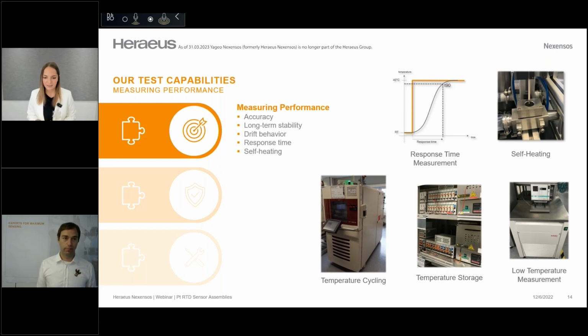This test is also specified in the DIN norm. A very standard test setup would be to expose the sensor to its maximum operating temperature for 1,000 hours. And sometimes maybe not the high temperature region might be decisive, but the low temperature region. That's why we also have in our validation analysis center a low temperature measurement, for example, to measure the cryo temperature range up to -196 degrees Celsius.